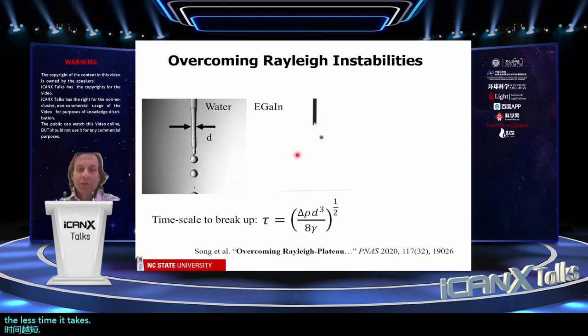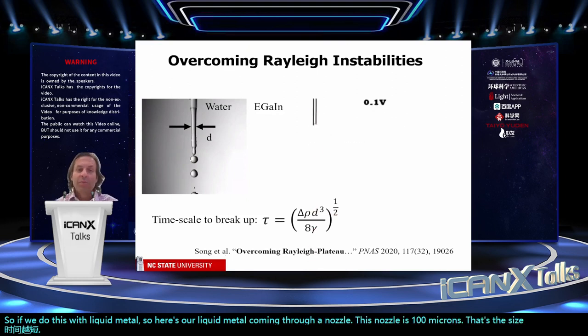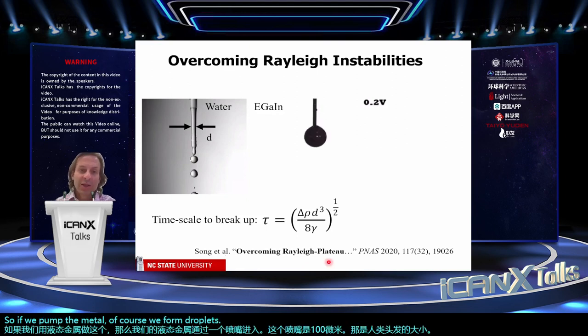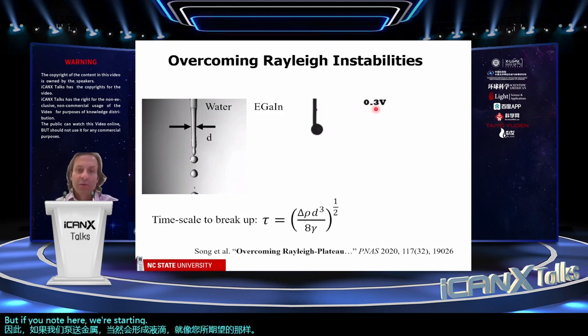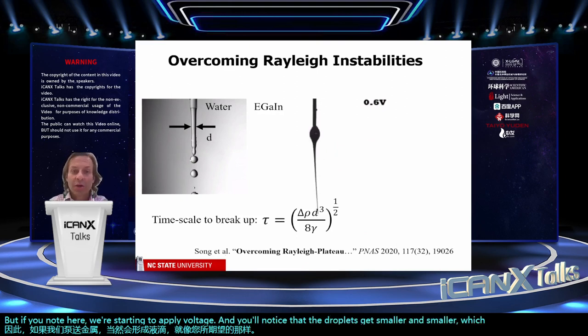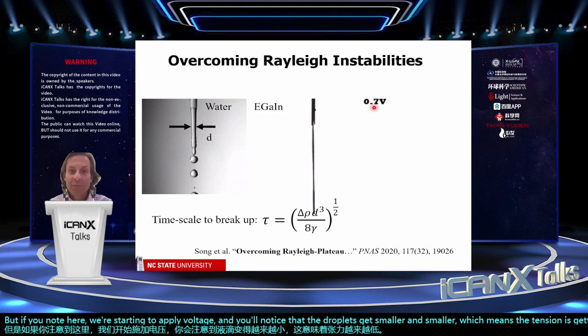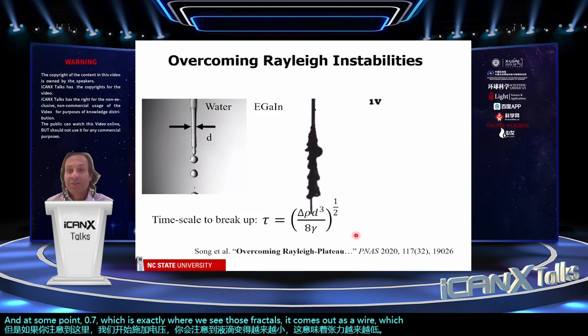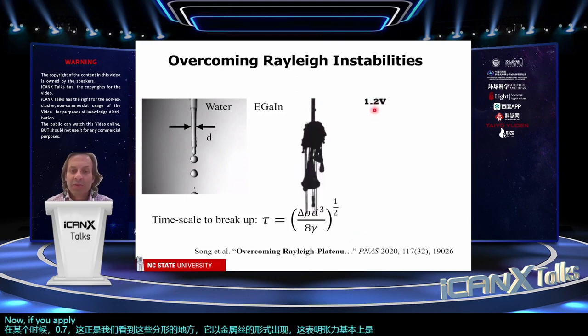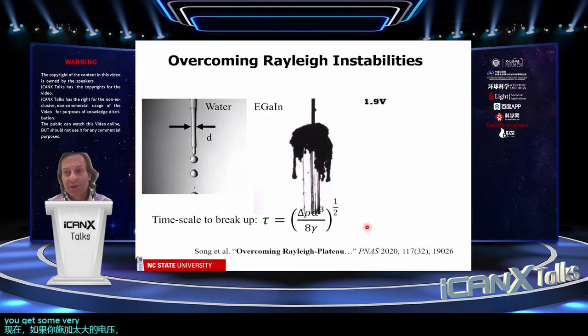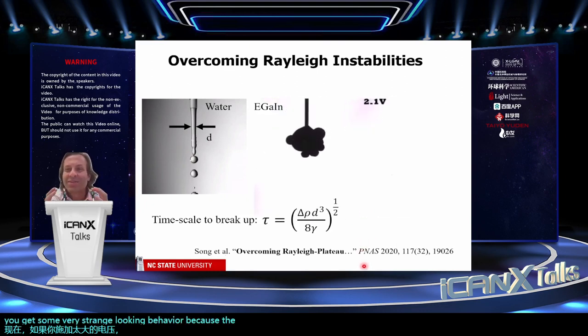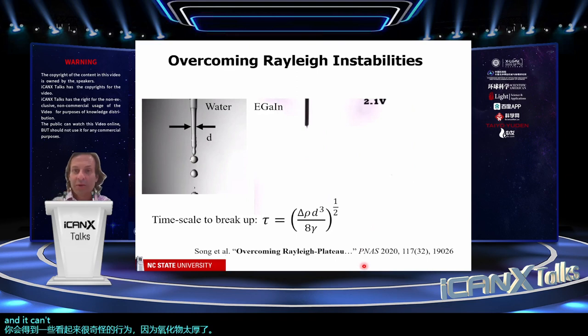So if we do this with liquid metal, so here's our liquid metal coming through a nozzle. This nozzle is 100 microns. That's the size of a human hair. So if we pump the metal, of course, we form droplets, just as you would expect. But if you note here, we're starting to apply voltage, and you'll notice that the droplets get smaller and smaller, which means the tension is getting lower and lower. And at some point, 0.7, which is exactly where we see those fractals, it comes out as a wire, which suggests the tension is basically zero. Now, if you apply too big of a voltage, you get some very strange looking behavior because the oxide gets too thick and it can't flow regularly.